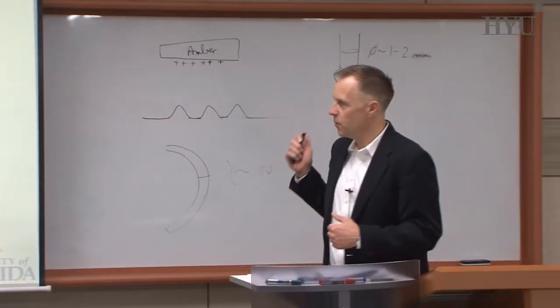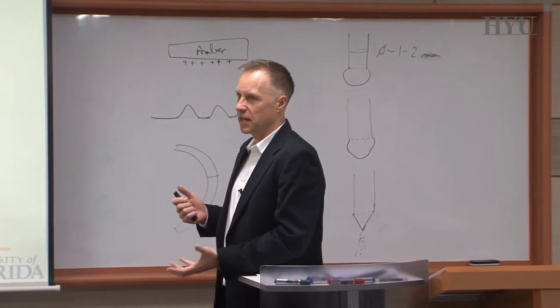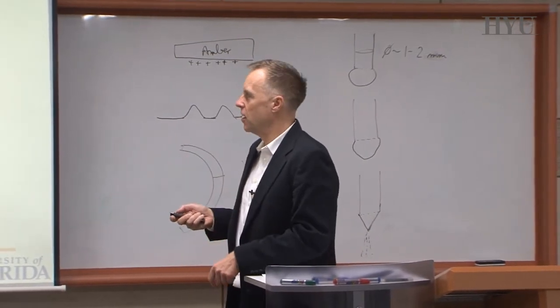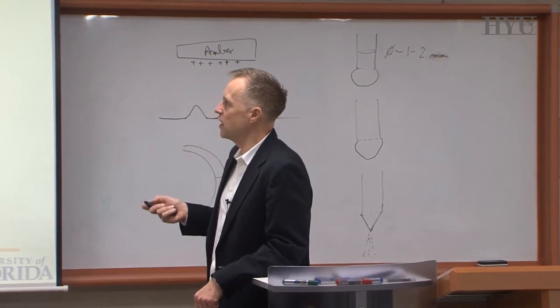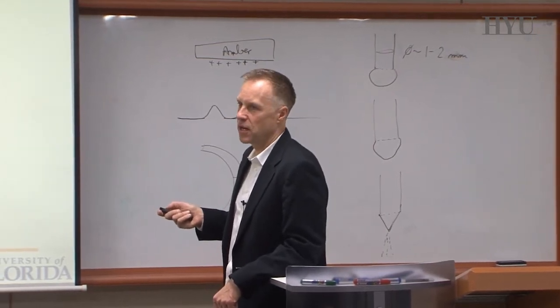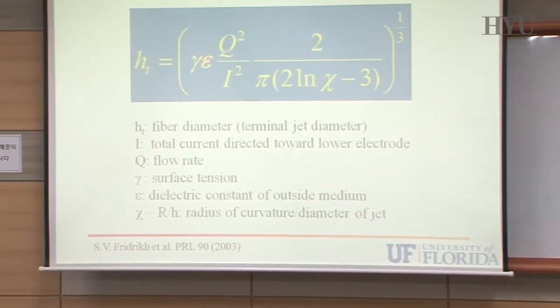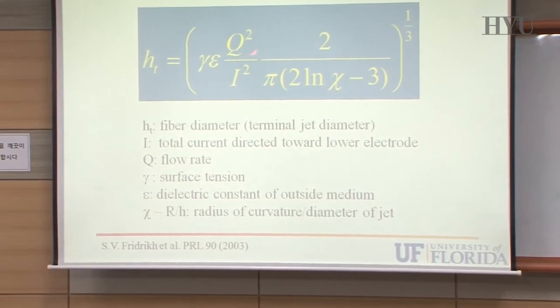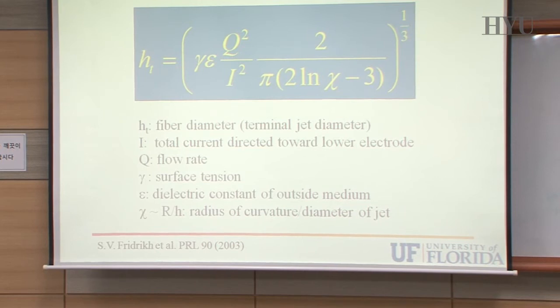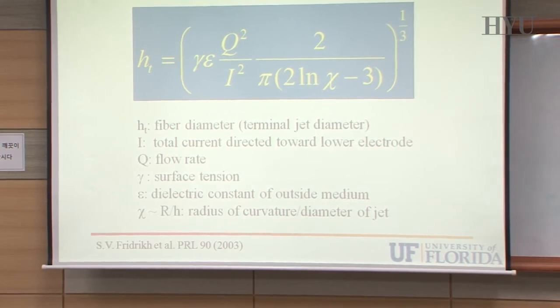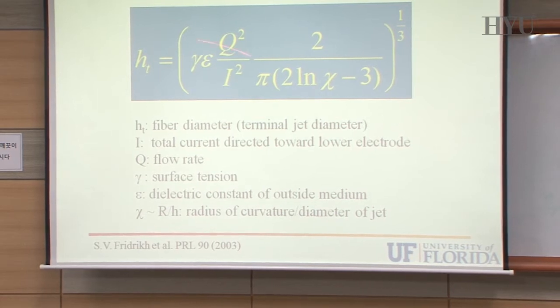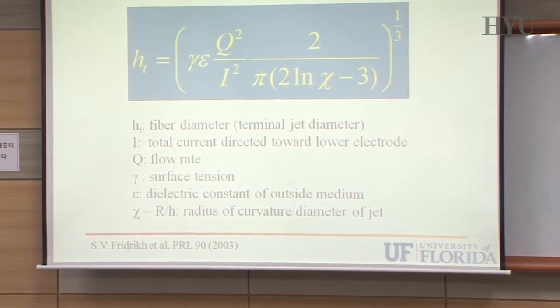But the good thing is, with this equation, if you have a system that you can electrospin that falls within the range of such an equation, then you can actually tell whether you have a chance to move it towards nanofibers. Yeah? If you have a certain flow rate and you make 10 micron thick fibers, then you can plug it into this equation and see how slow the flow rate has to be to come to this value. And then if you see the flow rate has to be so small that my machine can't handle it, or that it's unlikely to be there, then yeah, you can easily predict that. That's the nice thing about such an equation. You can tell whether you have a chance of actually getting there.